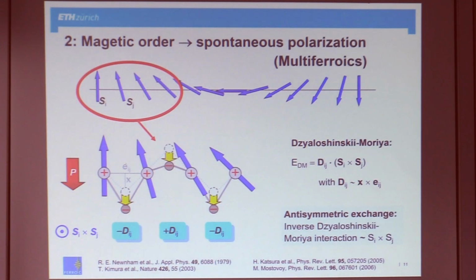Okay. Then you can also have it the other way around, namely a magnetization inducing a ferroelectric polarization. This brings us to multiferroics, which are discussed a lot for this coexistence of magnetic and electric order. A typical structure that can induce a spontaneous polarization from magnetism is a spin spiral. So, for instance, of this type, this is rather a spin cycloid. The spins rotate by a constant angle from site to site, and then you get this spiral. The thing is that this spiral breaks inversion symmetry. Exactly as I said, you need time reversal symmetry broken and spatial inversion symmetry broken. In detail, it means that there is an energy contribution from the Dzyaloshinskii-Moriya interaction, which is proportional to the cross product, the vector product of two neighboring spins.